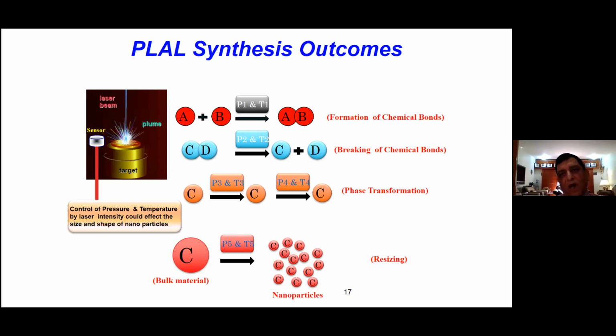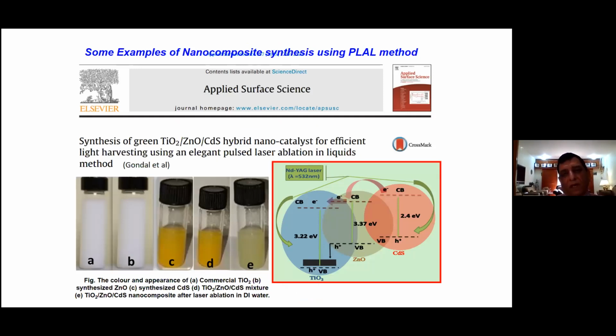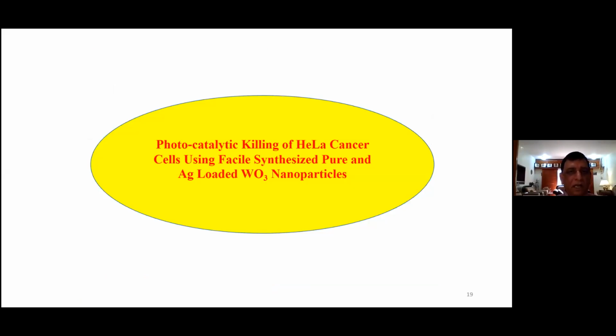For example, we can form new chemical bonds. We can break chemical bonds by laser. We can do phase transformation of the crystals which we synthesize, or we can resize the nanoparticle from bulk particle, just by controlling the laser parameters. And this is one of the examples which we have. You can see a nanocomposite TiO2, ZnO, CdS, and you can see the band gap. CdS is 2.4, which is in the visible region, while zinc oxide is 3.37 in the ultraviolet, and TiO2 is 3.2, also ultraviolet. So when we make this nanocomposite, we can very easily bring it to the visible light region, and we can make many applications for water treatment or other applications using sunlight.